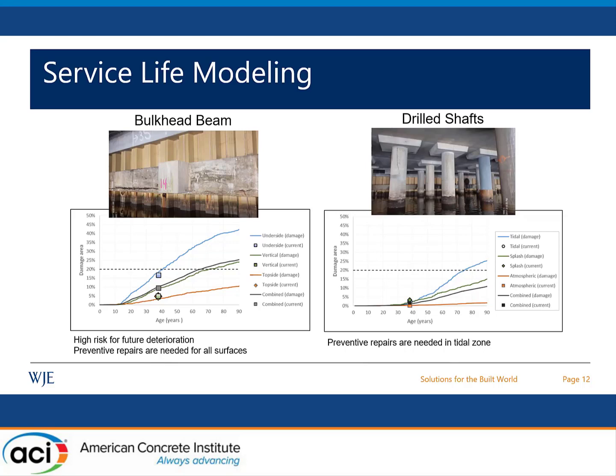And a similar approach we used for the drill shaft, where we verified our model using our field investigation results. And we found also a good correlation between the percentage of damage predicted using our model and also the percentage of damage from our field investigation. And based on the service life modeling results, we recommended preventive repairs needed in the tidal zone to achieve the additional 50 years of service life.